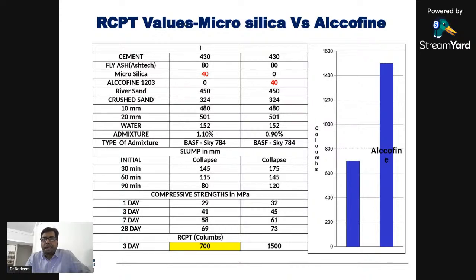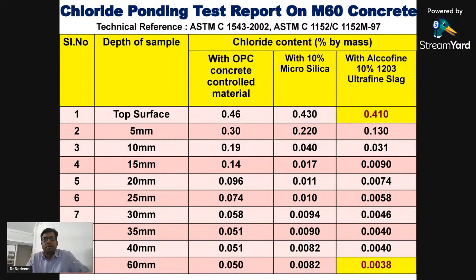So if you see, we tested it. In one micro silica, it is giving a value of say 700, and in the other case, it is giving 1500 as per RCPT. Once we did a pond test, the values are totally reversed. If you see the pond test, the values are quite low as compared to the RCPT values. So these are the drawbacks. Unless we draw a correlation of RCPT with the ponding test, the actual test with the same concrete, misleading results will come if you use RCPT independently.